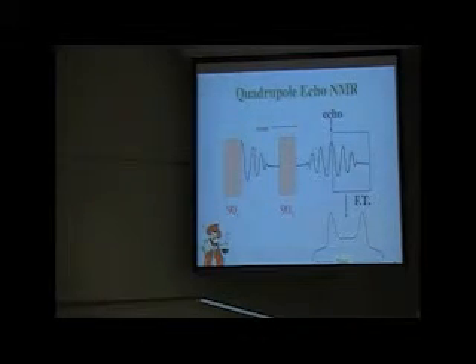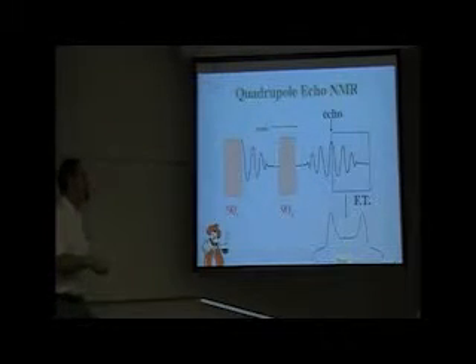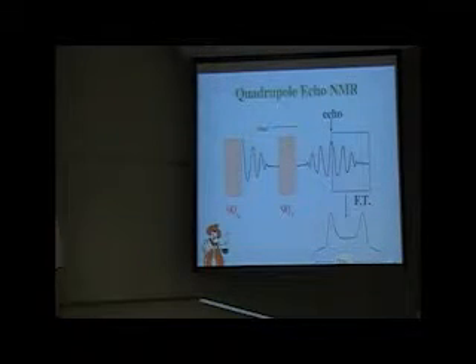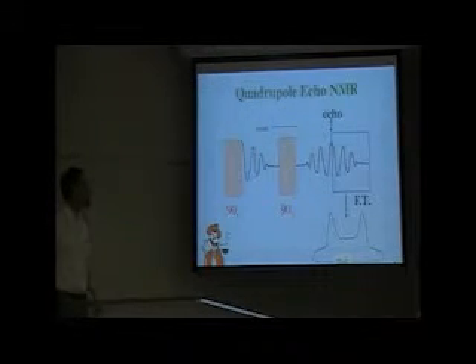Okay. So you're in that range, and there's weird things, and there's cool things too, like a hydride can be like minus 30 parts per million, and a hydrogen bonded thing can be up by 12, 15, whatever. But 0 to 10 parts per million typically corresponds to, on a 400 megahertz NMR, 4,000 hertz in sweep width. This spectrum that I'm looking at here has a total width of at least 250,000 hertz. So it's really, really wide. It's a solids thing. This is like brute force NMR. And the reason we do brute force NMR is I'm not smart enough to know how to do finesse NMR, so we just have these big old power amplifiers, and we just bash the system a little bit.